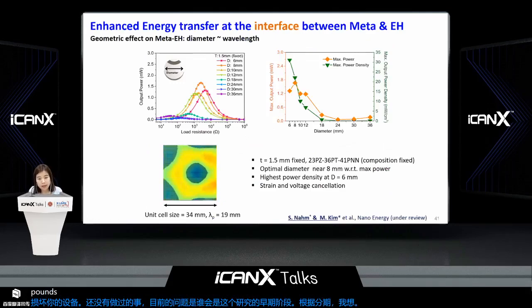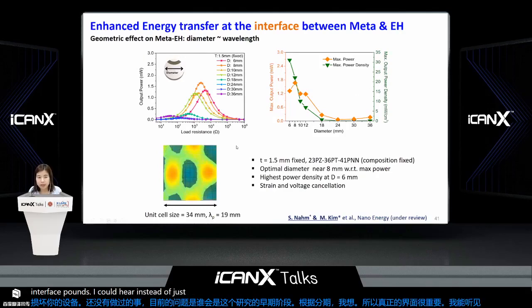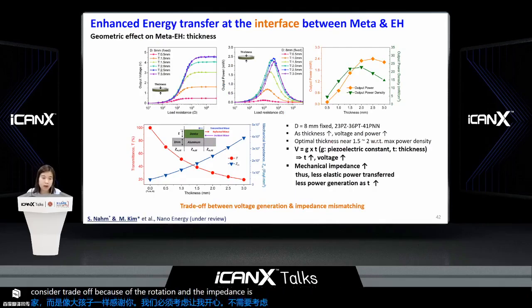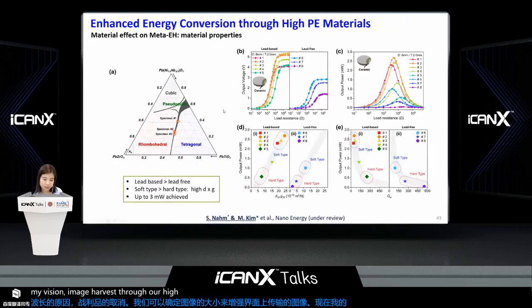What we found is that instead of just using big piezoelectric energy harvesters, like big diameter or thick piezoelectric ceramics like here, we have to consider the mechanical impedance, the trade-off between the voltage generation and the impedance mismatching, or we have to think about the voltage cancellation effect because of the wavelength size. And depending on the phonon crystal size, the unit cell size or wavelength size, we can determine the sizes of the energy harvester to enhance the energy transfer at the interface. And like in vibration energy harvesters, the product of a high piezoelectric coefficient d times g is the best for the best performance of energy harvesting using phonon crystals as well.